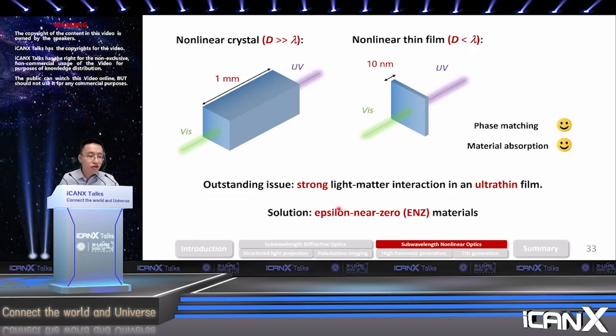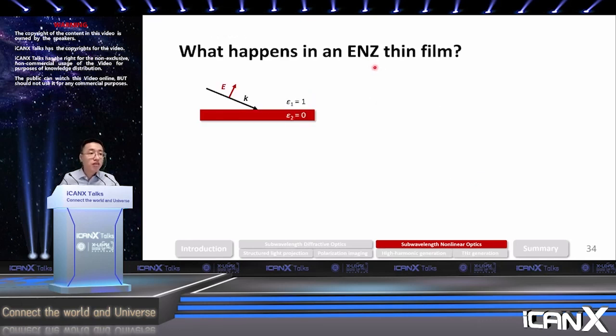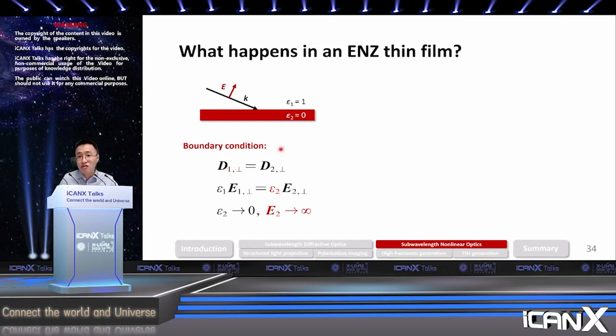Our solution here is to use so-called epsilon-near-zero, or ENZ, material to construct this nonlinear thin film. By epsilon, we mean the permittivity of the material; the refractive index of a material is basically the square root of epsilon. So let's see what will happen inside a thin film made of this ENZ material. Let's assume that we have p-polarized light with oblique incidence from air into a material with permittivity equal to 0. According to the boundary condition derived from the Maxwell equations, across the interface of two materials the normal component of the displacement field is going to be continuous.